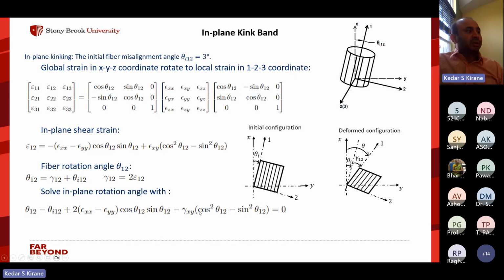And in each time increment, we solve for this angle. And once we solve for this angle, the system of microplanes is then rotated accordingly. So in each time increment, the orientation of the cylinder is changing with local shear. So this is for the in-plane system.